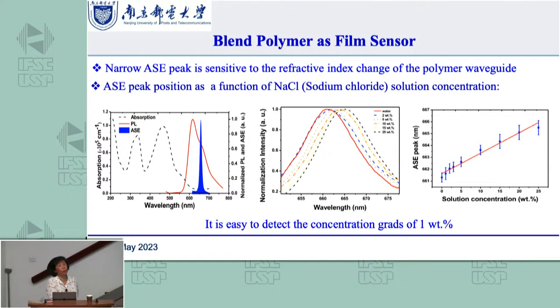We also tried to use the laser peak to test some solutions, because the laser peak is so sharp compared with the PL peak. If this laser or ASE peak shifts 1 nanometer or 2 nanometers, it's very clear, so you can easily identify it. But if the PL spectrum shifts 5 nanometers, it's hard to say whether it really shifted or not. So we use this narrow ASE or laser peak to identify solutions, and this can give you very high resolution.